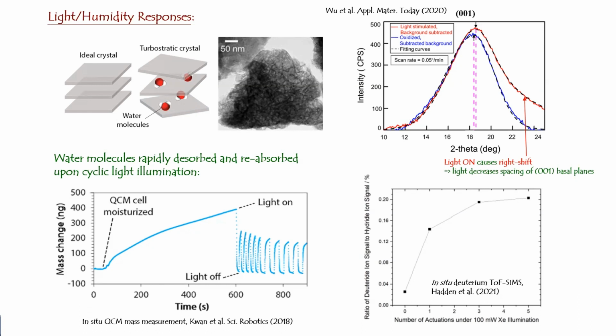Another proof is that we can measure the mass of the material with or without the light. So every time we switch on the light, the material actually becomes lighter in weight. So something is coming out of the material. And then when we switch off the light, the weight regains to more or less its original value. So something is now sucked back into the material to increase the weight. And then this group in Imperial, after seeing our paper, they performed this very interesting experiment. They used deuterium, which is heavy water. Basically, these water molecules are labeled.